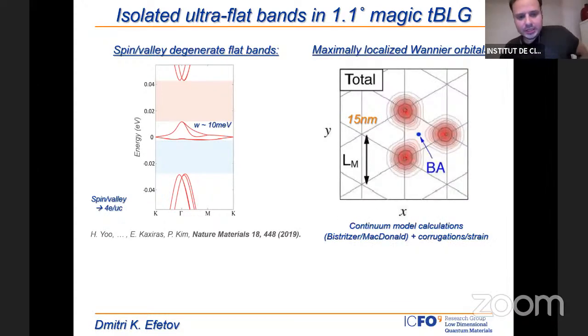And in return, what these flat bands also mean is that we get maximally localized Wannier orbitals. In other words, flat bands mean that the kinetic energy, or the Fermi velocity, diverges to 0. That means the electrons like to almost stay in place, and therefore the kinetic energy is small, and the Hamiltonian is dominated by interactions. And those maximally localized Wannier orbitals have their maxima in the center of the moiré itself.